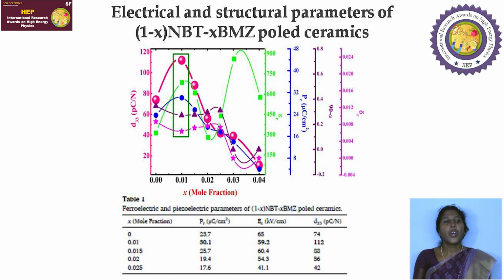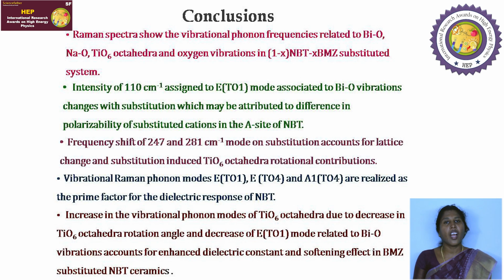So the conclusion is, from the Raman spectra, we can get all the phonon vibrational frequencies related to BiO, NaO, TiO6 and oxygen phonon vibrations. Now, the intensity of the ETO1 mode, which is assigned to BiO, that is bismuth oxide vibrations, is changed due to the difference in the polarizability of the substituted cations in the A site. Now, the shift in the frequency region, the B mode, that is 247 and 281 centimeter to the power minus 1, is related to the change in the TiO6 octahedra rotational vibrations.